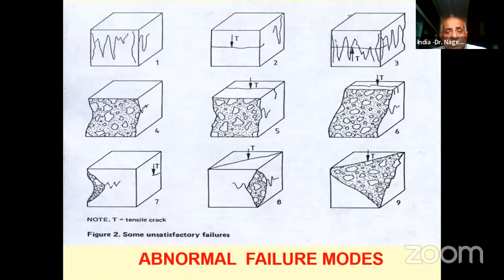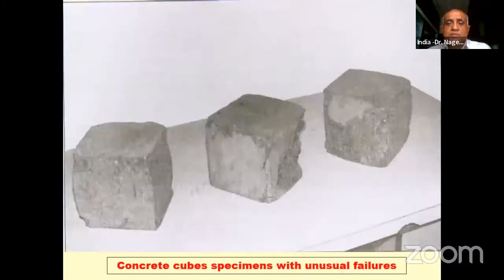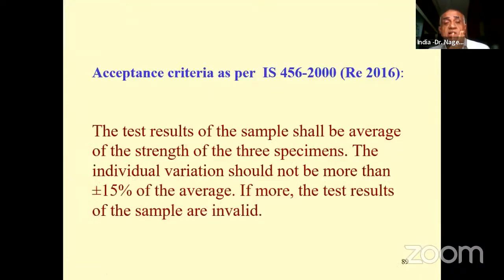If you look at these photographs, you should not get horizontal cracks when you are testing the concrete cube. Horizontal cracks are not supposed to occur. If horizontal cracks occur, that means the surfaces are not plane. There is an eccentricity, and this eccentricity results in crack development. So these are the specimens with unusual failures.